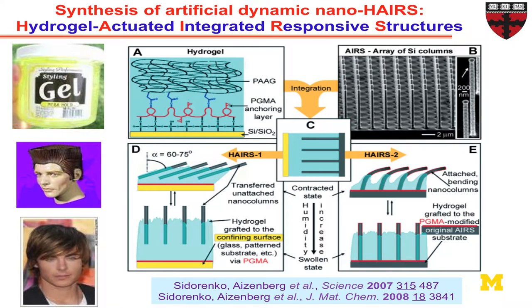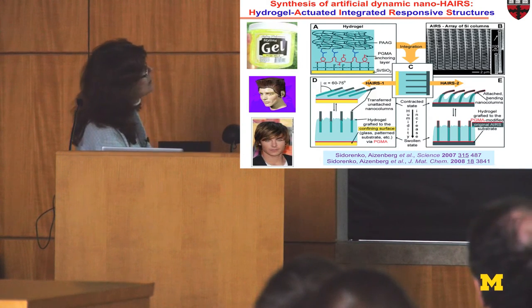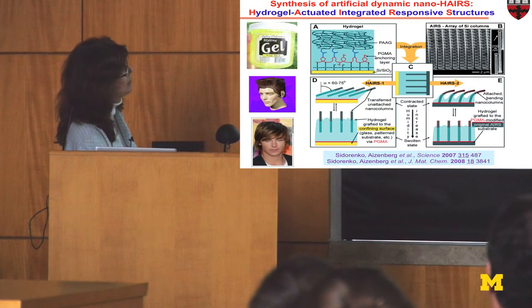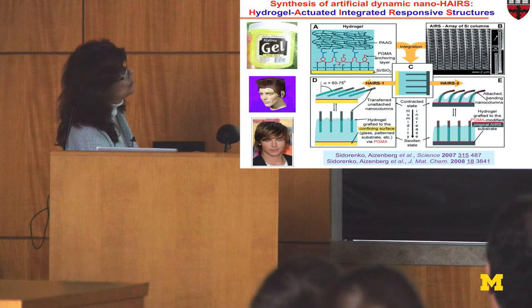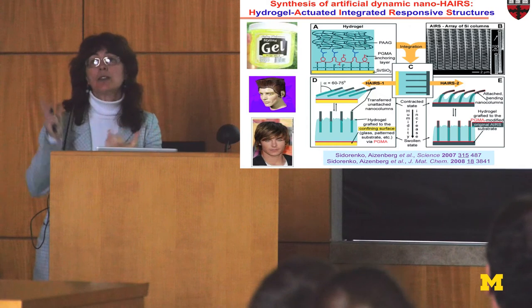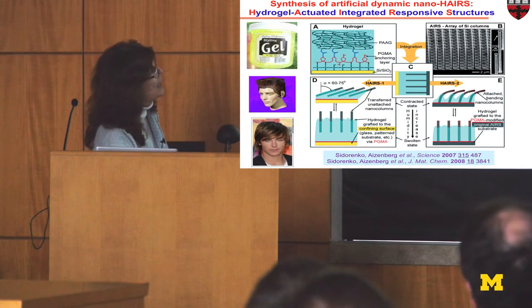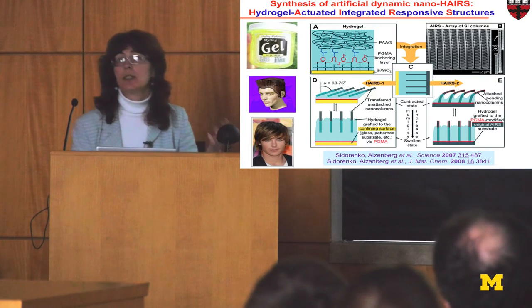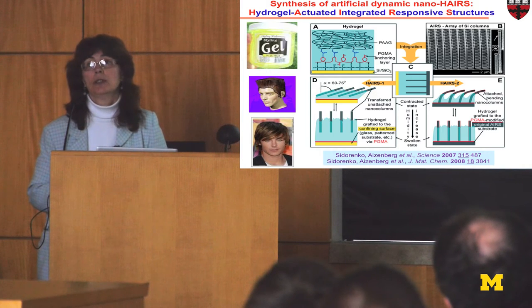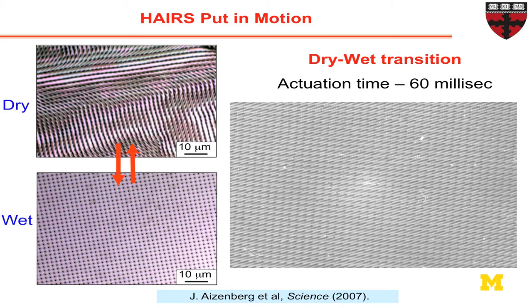So structures alone can do something, the gel alone can do something, but if I now combine them in the simplest possible way, and we call it styling with the gel, it is the high aspect ratio structures and the hydrogel that is being synthesized within this structured hairy surface. So what happens then is that this gel will create a structure that will either expand or contract, and as it does that, the high aspect ratio features would either bend or tilt, depending on the type of connection, and upon response to either humidity or other stimuli, would put your materials in motion.